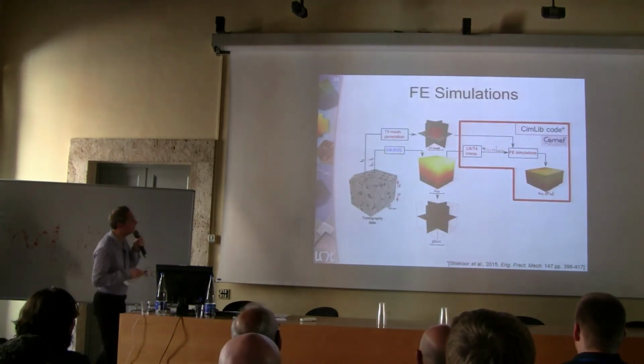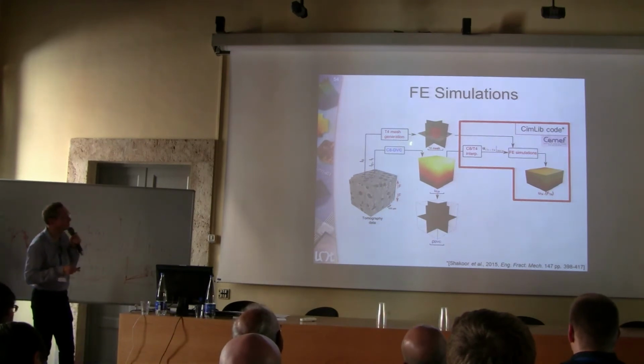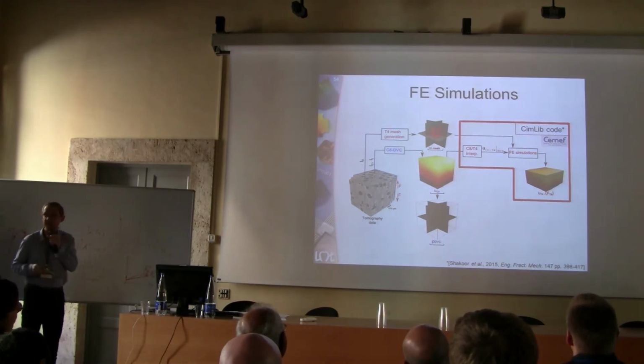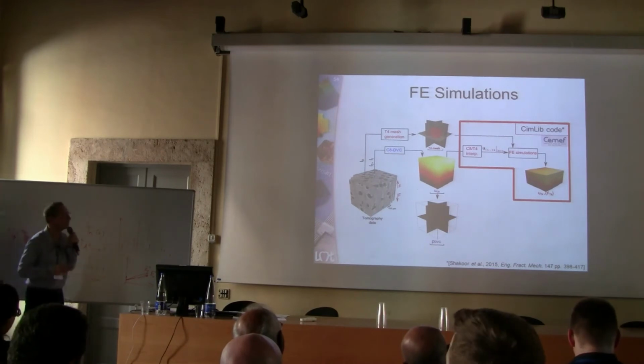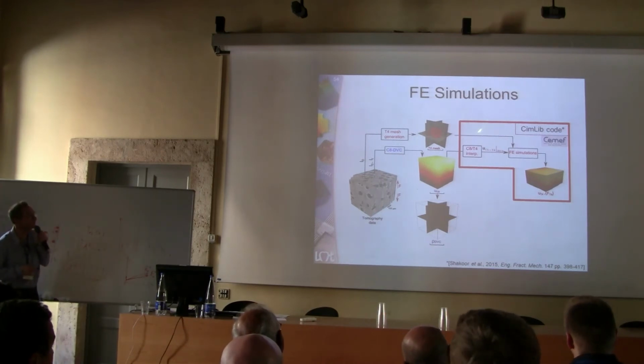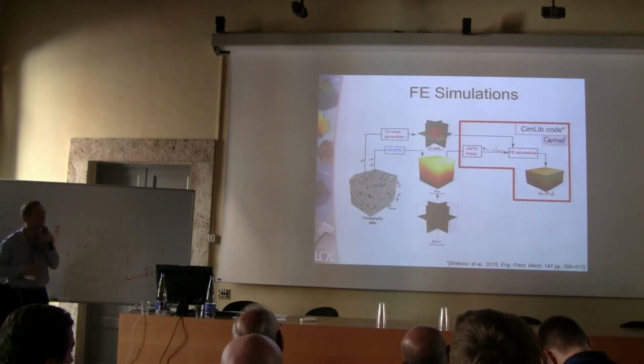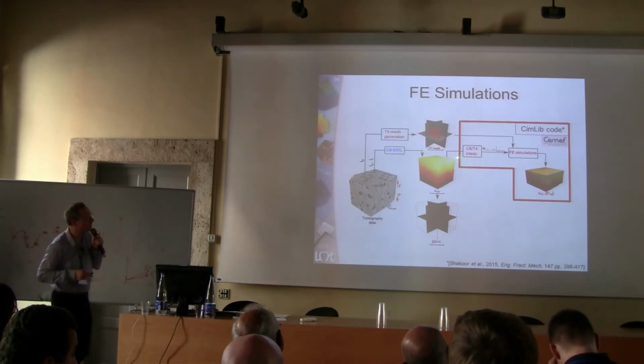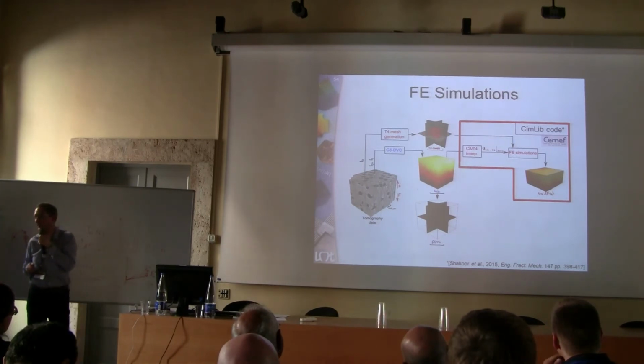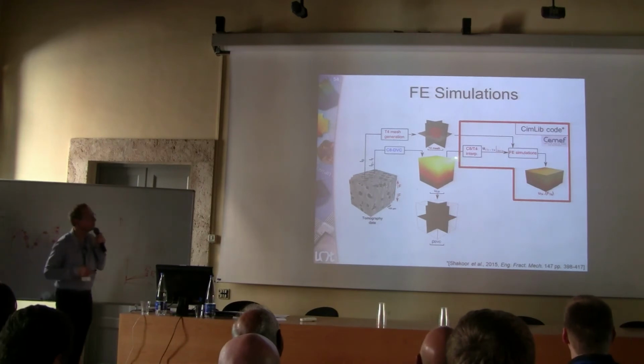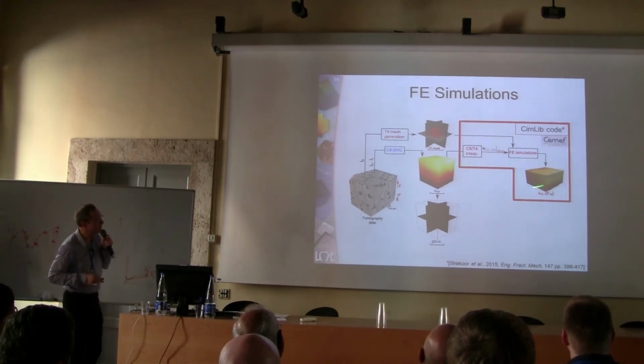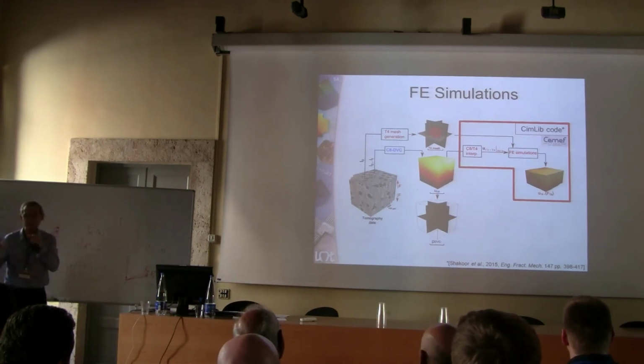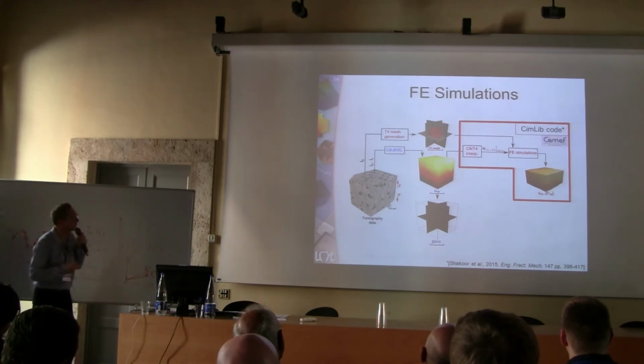The fact that we have here a mesh that is repositioned in these volumes allows you now to compute the response of this volume by prescribing the measured boundary conditions. Which means that now you have a simulation that is consistent with the underlying microstructure and the boundary conditions.